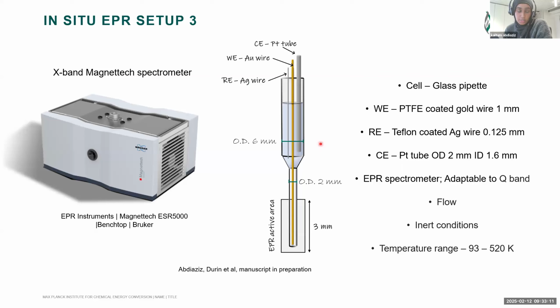So the third setup that I have developed is for the Magnettech, the benchtop spectrometer. In order to get a setup that works at room temperature, I had to significantly reduce the volume of my EPR tube. Here I have a small tube, which is about 2 millimeter diameter at the bottom, connected to a much larger one, which is a 6 millimeter outer diameter. My working electrode is the gold wire that goes all the way down to the bottom. Then I have my platinum tube as my counter, and a silver wire as my reference electrode.